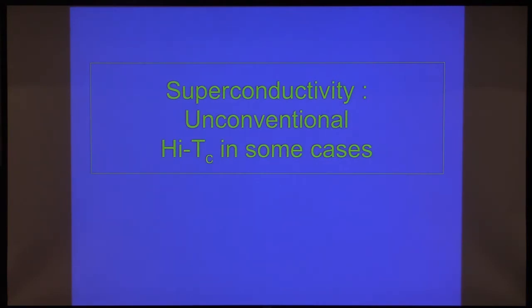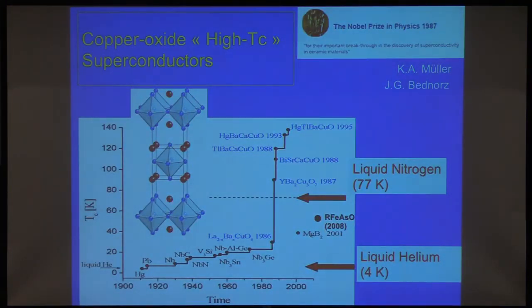Of course, it would be impossible to talk about this field without mentioning the class of materials that really put materials with strong electron correlations back under the limelight in the late 80s. And these are high Tc superconductors. This is not going to be a talk about high Tc superconductors, but I'll sometimes mention them. So you know very well that around 1986 there was a real revolution in the field of superconductivity, in which all of a sudden the transition temperature of known superconductors increased by a huge jump over a period of just a few months, and a new family of materials was discovered, all based on copper oxides, in which the transition temperature can easily overcome liquid nitrogen.